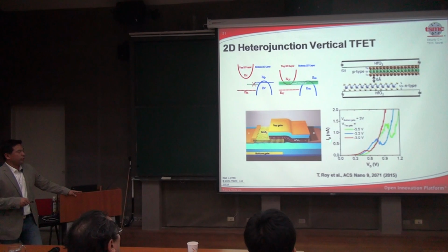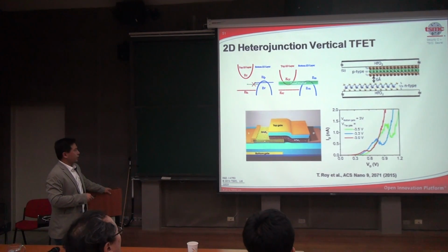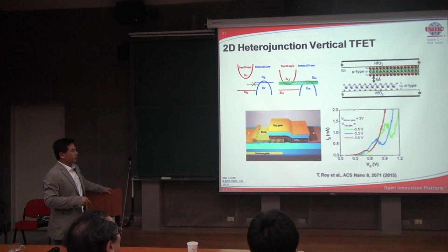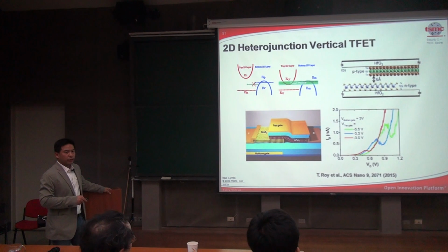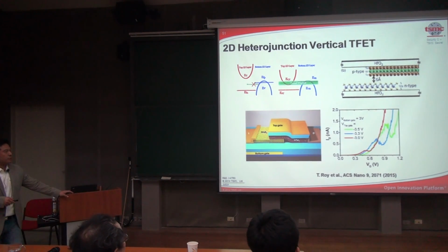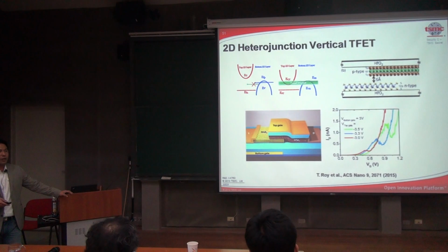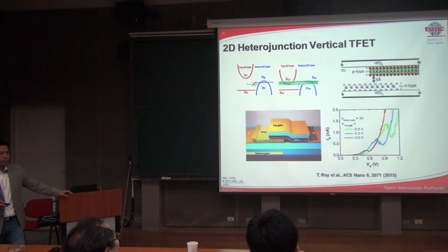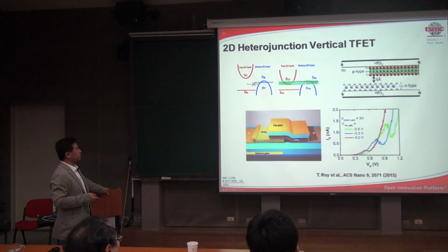And this is one of the preliminary results that was made on MoS2 and tungsten diselenide. One of them is N-type, the other one is P-type. That shows a very pronounced NDR, negative differential resistance behavior, indicating the tunneling current between the two materials. So this is not yet a tunnel FET, but shows the direction to go to this vertical FET. However, why do we want to use this vertical FET? The advantage is that you can increase the overlap area to give you a larger tunneling current that could be competitive to MOSFETs.